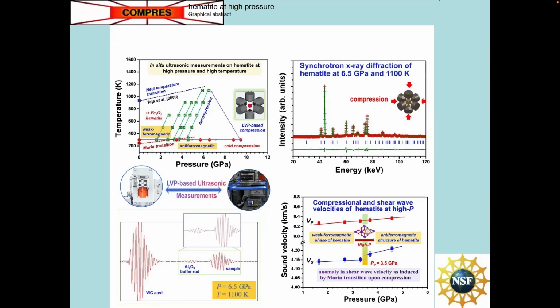And this is one recent paper by Zhou et al., including Irifune. And the interesting thing is, you have to be careful when you measure hematite, because if you measure it as a function of pressure at room temperature, the compressional wave velocities are very smooth. But if you're not very careful, the shear wave velocities, which I only measured to 3 GPa, if you measure them beyond that, there's a kink.